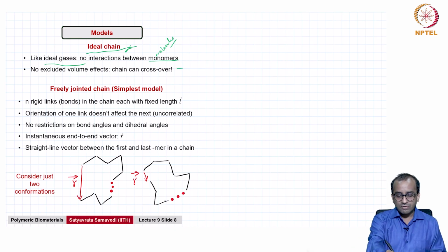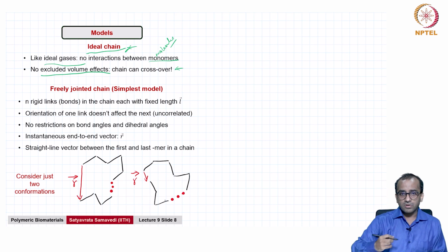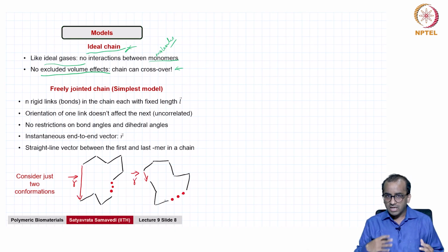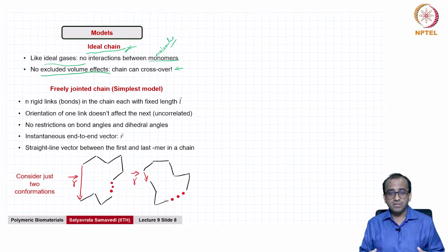Another very important idea for ideal chains is that ideal chains do not assume excluded volume. So, excluded volume effects are ignored. We will look at this in more detail in a later topic, but for now one way to understand what excluded volume is: when polymers keep doing this dynamic fluctuation, because these molecules occupy volume, you can't have chains cross paths or go through or intersect, or no two polymeric segments can occupy the same point in three-dimensional space.